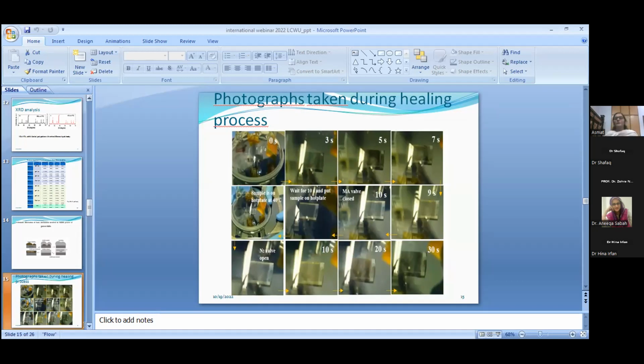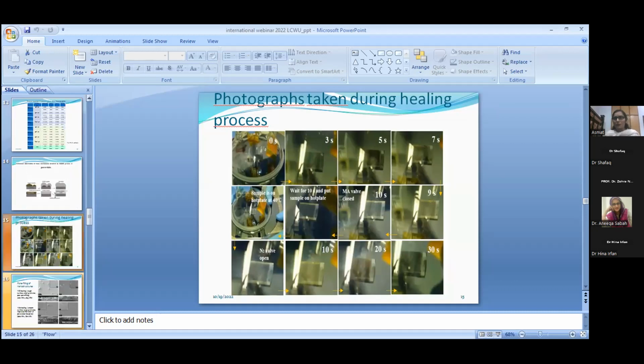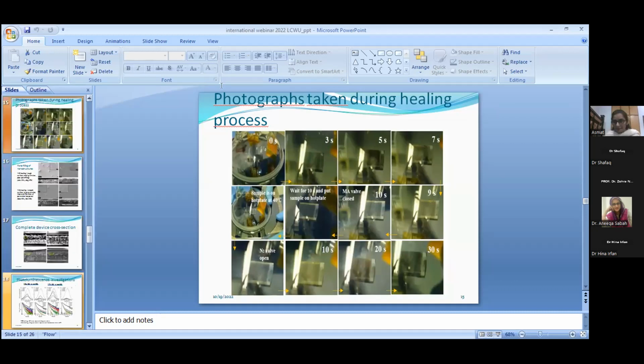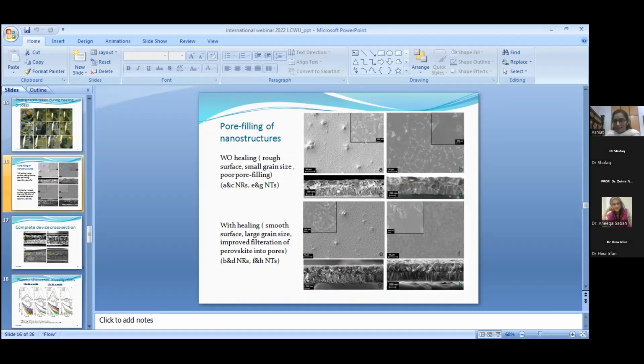Now we have the pore filling of the nanostructures. You can see that these are without healing and these are with healing. So without healing, we have a rough surface with small grain size and poor pore filling. You can see from this structure, we have the pore filling here and here. But with healing, we got a smooth surface with a large grain size and a very improved infiltration of the perovskites into the pores of both nanorods and nanotubes.